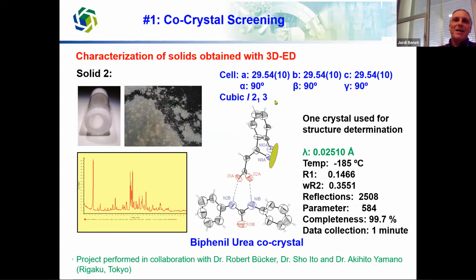I mean, this sounds very easy, but of course we need a lot of preparation because we measured at a low temperature. So we cryo-prepared the sample and we collected. But in this case, since it was cubic, we had only to collect one crystal and we got the structure solved. After this, we simulated the powder diffraction and compared it with the bulk of the solid, and it's the same, so we could quite easily characterize this compound as a co-crystal.